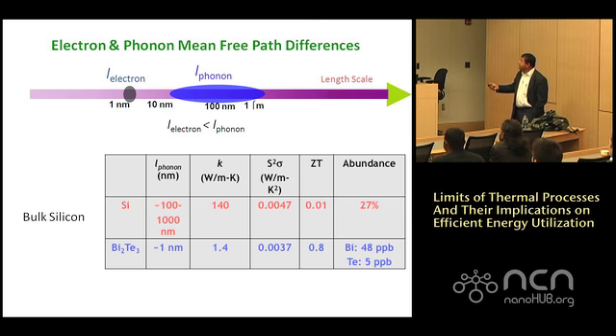So, this is silicon. The mean free path is anywhere from, depending on the wavelength of the phonons, 100 to 1,000 nanometers. Bismuth telluride is 1 nanometer or so. The thermal conductivity as a result is 2 orders of magnitude higher because the mean free path is 2 orders of magnitude higher. On the power factor side, the numerator, the electronic side, silicon is actually a little bit better than bismuth telluride, but it's about the same number. And so this ZT is about 0.8, and this is 2 orders of magnitude lower, primarily because of thermal conductivity. Abundance: this is 48 parts per billion. Tellurium, 5 parts per billion. This is 27% of the Earth.